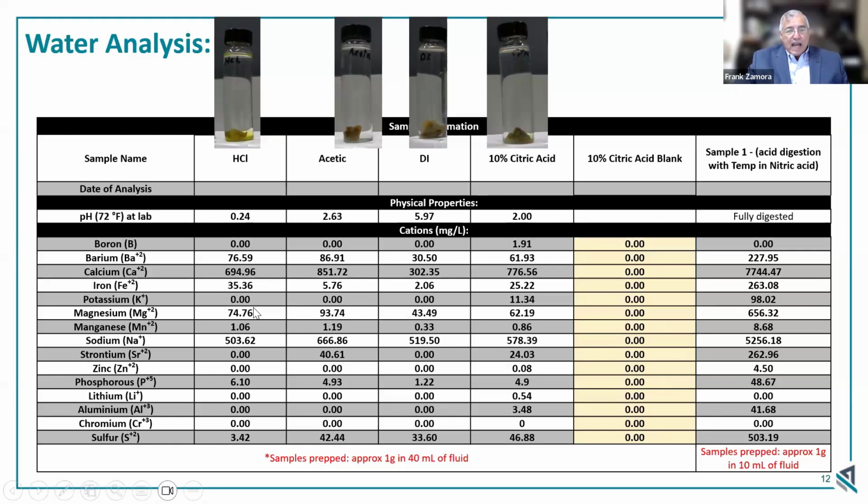So for hydrochloric acid, even though it appeared it did absolutely nothing to the solids, the salts appear to have come out, which stands to reason, because sometimes when you look at these samples and you're going to hydrochloric acid, they seem to get really tighter. They shrink in size, but they get tighter and firmer. And that could be simply because we're pulling all the salts out. And here's pretty good evidence that the salts actually all came out.